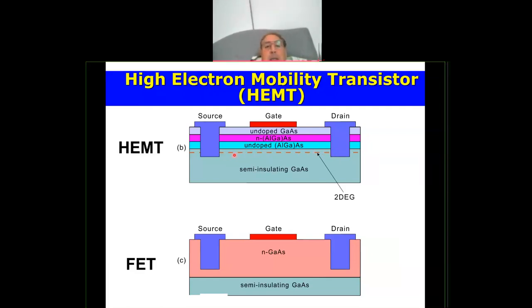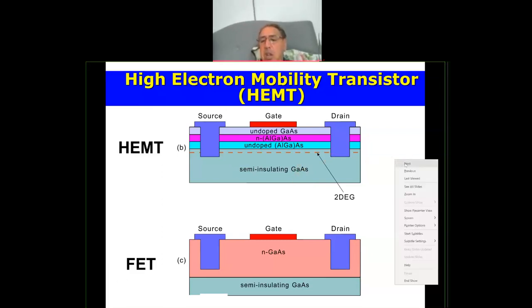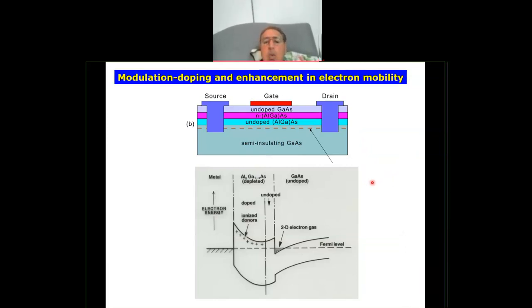So that means there would be less scattering, which means that you're going to increase the mobility of the electrons, which means you increase the frequency of these devices. So this is what we call high electron mobility transistors, because now this will operate very, very fast, because there's nothing to stop the electrons or scatter them. So you can see a very simple idea. So this is what we call high electron mobility transistors. And I'll show you some applications. But just to show you here what it means.